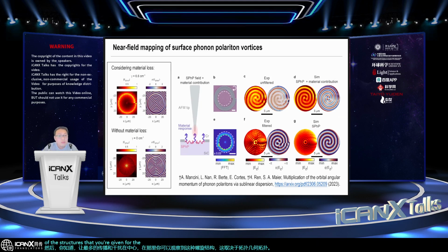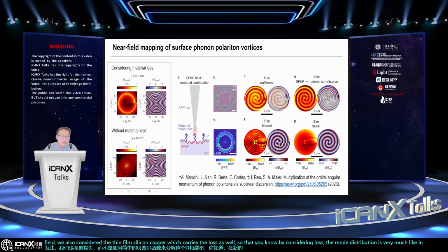For this, we also consider the loss, rather than using the simple Bessel functions to decompose these OAM modes. In the near field, we considered the thin film silicon carbide, which carries loss as well, so that by considering loss, the mode distribution is very much like an interference pattern, rather than the case without considering loss, where you get a typical OAM pattern.